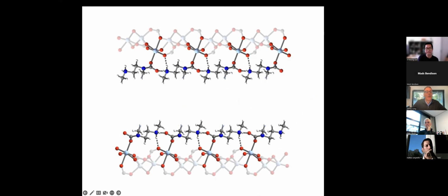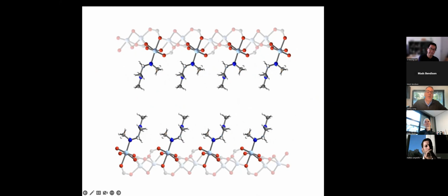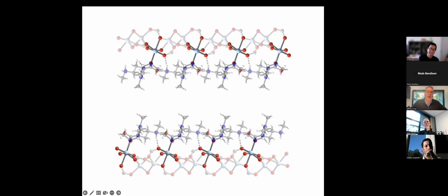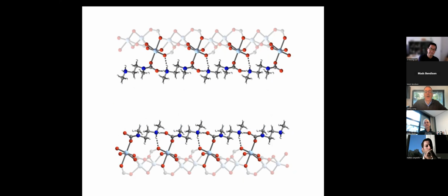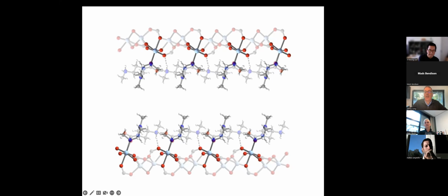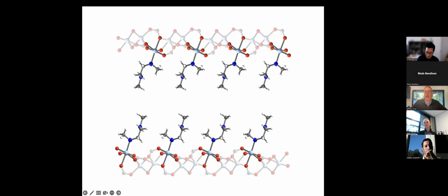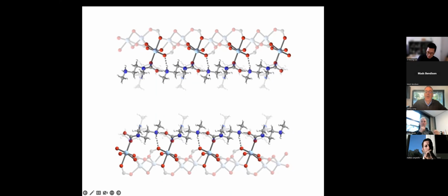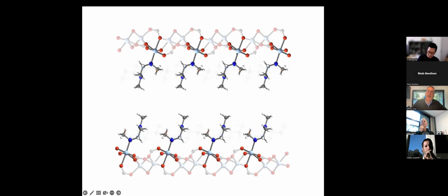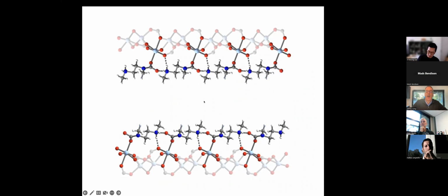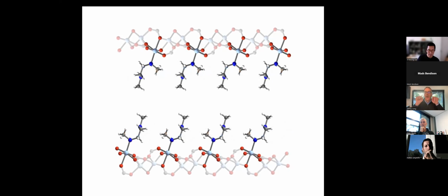And when CO2 adsorbs, it's going to insert into a metal-amine bond to form a metal-bound carbamate. And simultaneously, you'll transfer a proton from the backside of the amine you're inserting into to a dangling amine on the next site down the channel. That ammonium cation is attracted to the carbamate anion, and you can think of that as tugging on or activating this next metal-amine bond for CO2 insertion. So the product you get is a one-dimensional ammonium carbamate chain, one of those running along each corner of every hexagonal channel in the material.